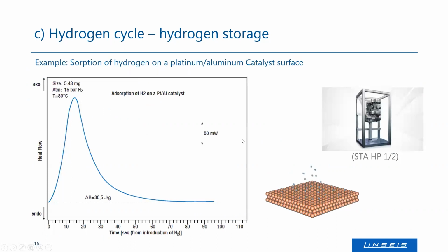Of course, for all these, so mainly for chemical storage and for sorption, we also have partners and customers who are doing research using our high pressure balances again. What we can do here is simulate sorption and desorption processes. So you can put in a sample, which can be an adsorber. You increase the pressure, you lower the pressure, so you can feed it with hydrogen at higher pressure. Then you lower the temperature, you lower the pressure. You see how much weight is gained and how much weight is lost when changing the pressure, changing the temperature. And by that, you can measure sorption curves like in this application example.